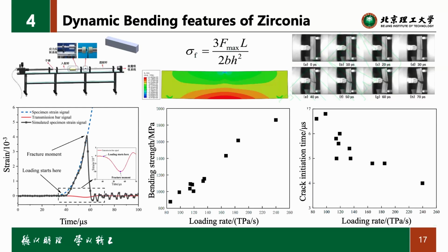This picture shows that the bending stress of the zirconia has a positive relationship with the loading rate. And this picture shows that the crack initiation time decreases with the loading rate.